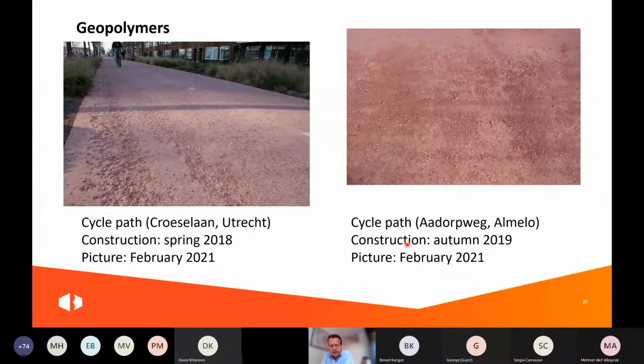I would say much more than you will find with regular Portland cement based cycle paths. I must say there are also good examples, for example, a roundabout in the Netherlands from geopolymers, which is still looking very fine after 3 years. But I would say more than 50% is substantially damaged.